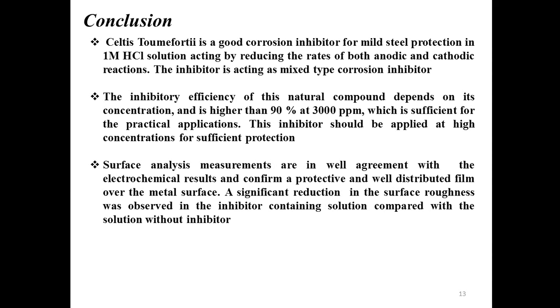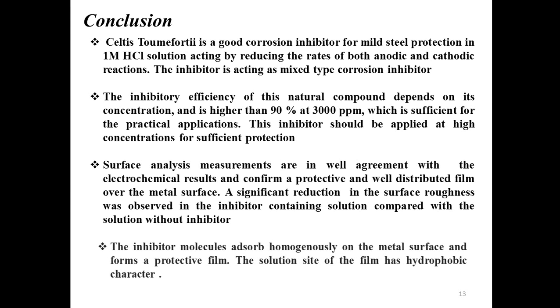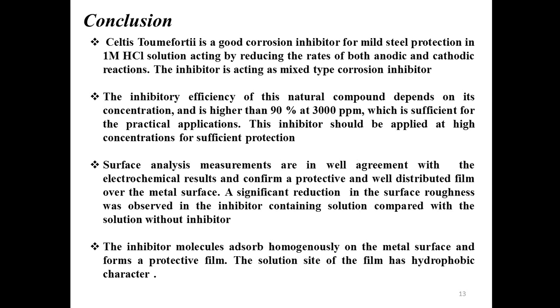Surface analysis measurements are in good agreement with the electrochemical results and confirm a protective and well-distributed film over the metal surface. A significant reduction in the surface roughness was observed in the inhibitor-containing solution compared with the solution without inhibitor. The inhibitor molecules adsorb homogeneously on the metal surface and form a protective film. The outer layer of the film has a hydrophobic character.